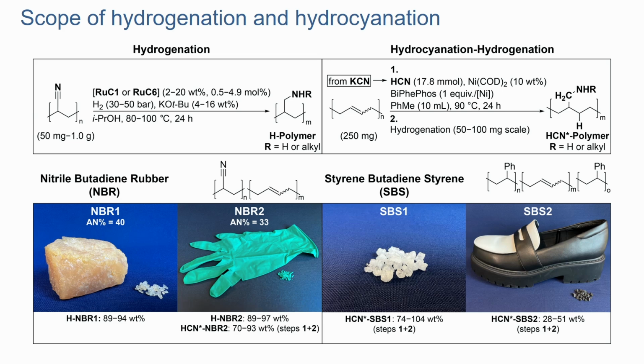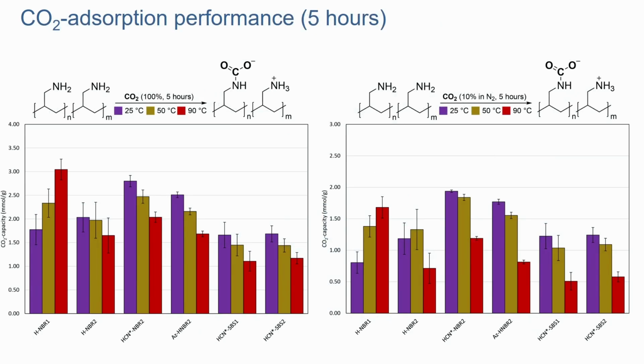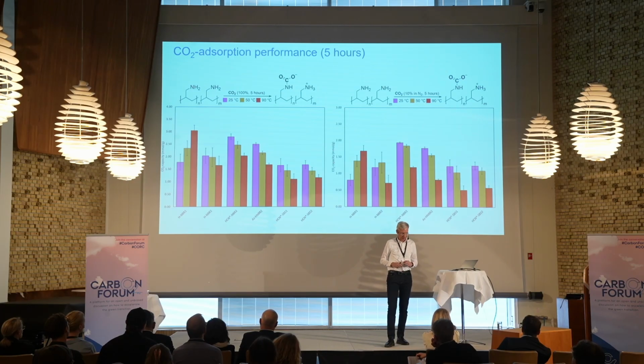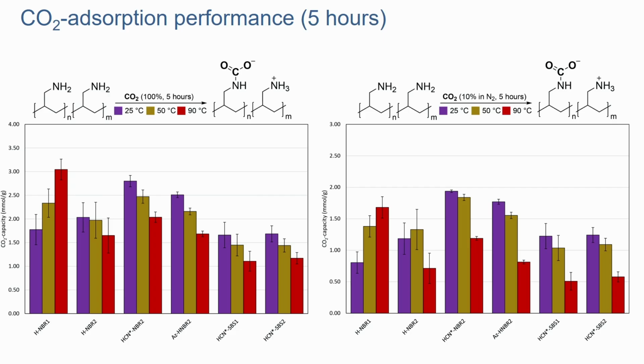And then we've also taken other materials, for example from a shoe sole, and converted that into carbon capture materials. Just to show you some of the details, these were the first results where we're measuring how much CO2 is binding to these materials over time, over 5 hours in 100% CO2. Some of these materials were doing pretty good. The best was at 90 degrees again, the one all the way to the left, with a capacity of 3 millimoles per gram, which is about a 14% weight increase.